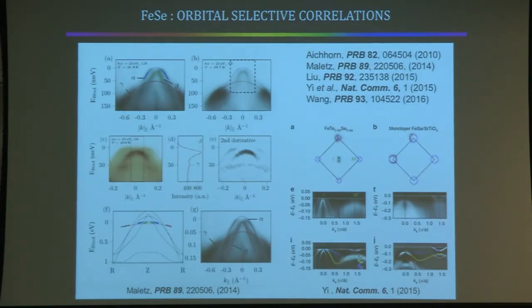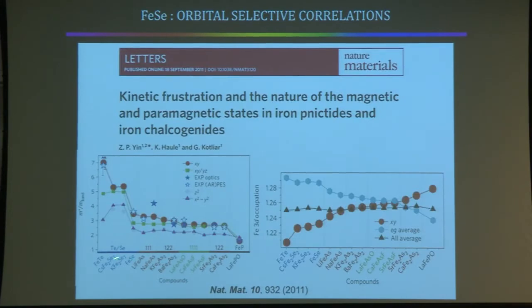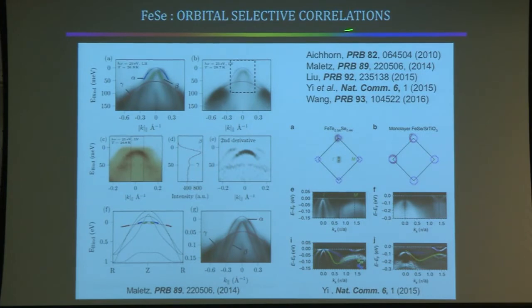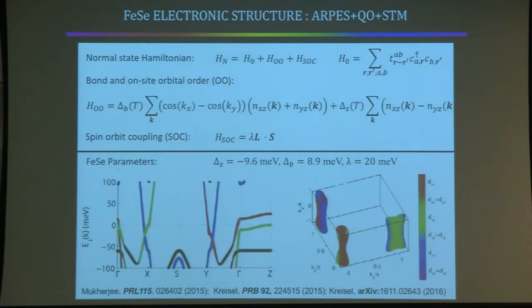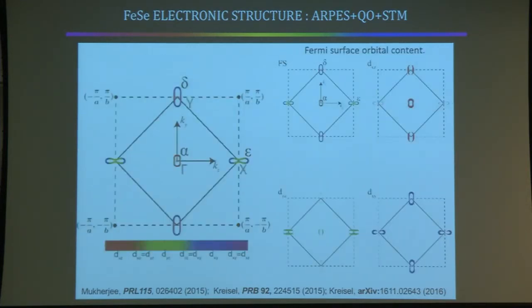Anyway, so we know that in this iron selenide compound, there are strong orbital selective correlations. That has been detected by photo emission. The bands near the chemical potential are much too flat. We made a band structure model working with Brian Andersen and Peter Hirschfeld for iron selenide, and it's our best match of photo emission, quantum oscillations, and our own data. We tried to parameterize the band structure. I'd be glad to explain this to anyone who wants to know, but putting aside all these details, it tells us the following thing.